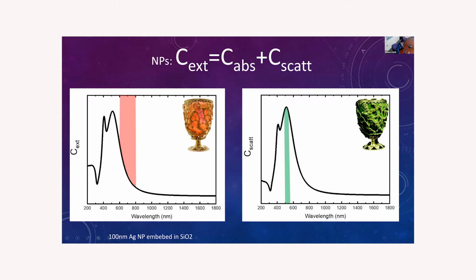For example, to explain the red color, we should say that if the light is going from inside the cup to the outside, the extinction means that all this light is either absorbed or scattered. So the only contribution that we are observing is the wavelengths that are not totally absorbed. In this case, we are in the red region of the visible spectrum. It's more or less like in the case of small gold nanoparticles in water, where, if you remember, the color is very red, like ruby color. And the maximum is more or less at the same wavelength, 510 or something like that.